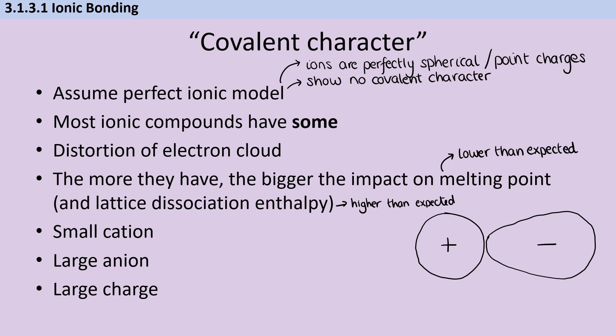So what's actually going on here? Well, basically, our positively charged cation is drawing the electrons towards itself. And this is particularly likely to happen if we have a small cation, because if you think about it, if you have the same amount of charge spread out over a smaller surface area, then the charge density is higher. And that means that the smaller cation is able to attract electrons more strongly than a large cation with the same charge. So, for instance, lithium chloride has more covalent character than potassium chloride, because lithium is a smaller cation than potassium is, even though they have the same overall charge. The second thing that increases the likelihood of covalent character is if we have a large anion. So the outer shell electrons on that anion, because it's large, they're less attracted to the nucleus because they're further away and they're experiencing more shielding. And therefore, it's more easy for them to be polarized and this electron cloud to be distorted. So this means that lithium iodide shows more covalent character than lithium chloride because iodide is a larger anion.